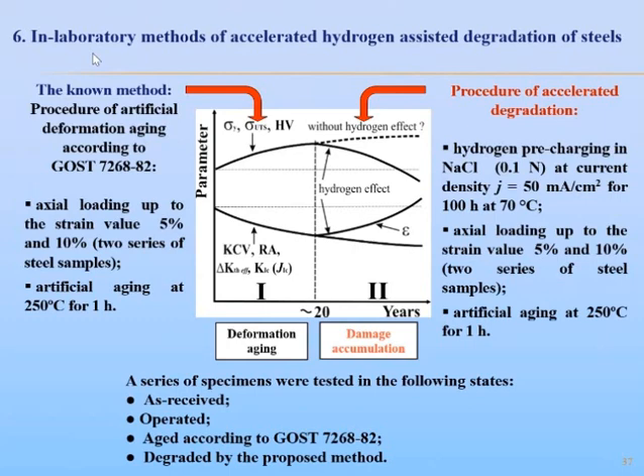And in order to reach the second stage of in-service degradation, we have to modify the method by including a step which causes intensive in-bulk damaging. This can be achieved by preliminary hydrogenation of specimens, and only after that, loading to a certain strain value and then artificial aging. The simultaneous action of hydrogen absorbed by metal and deformation will cause microdamaging in the metal.